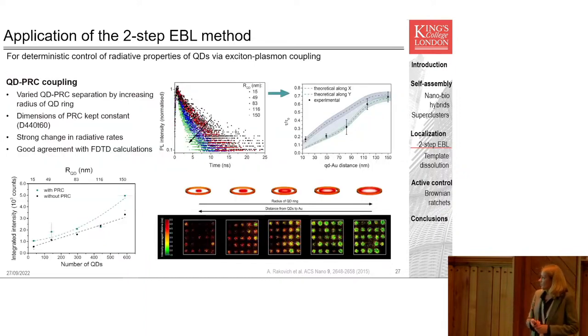We then went on to characterize our coupling, and you can see, for example, for an array of quantum dots deposited very close to the rings, you really do get more or less consistent intensity emitted from these structures, as well as a very consistent lifetime. And all of it follows the theory quite nicely as well. But of course, you may say that, well, okay, we're depositing quantum dots, but we're depositing in large areas. But can we actually precisely, deterministically place a single particle in a specific location on a substrate?